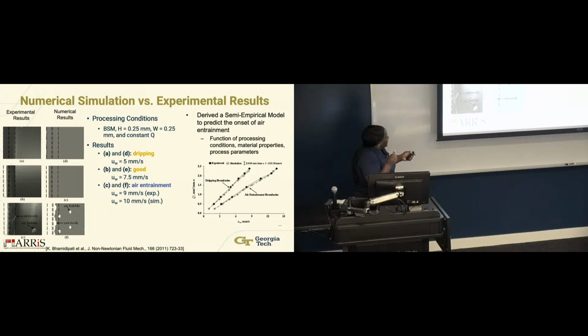It did that for the experimental data as well as the numerical data. Then for B and E, we see that the contact line is just behind the deposition region, and it's stable. There's no defects. The material is pretty pristine in both cases. And then we have the C and F, where we begin to see this structure we call a sawtooth formation.